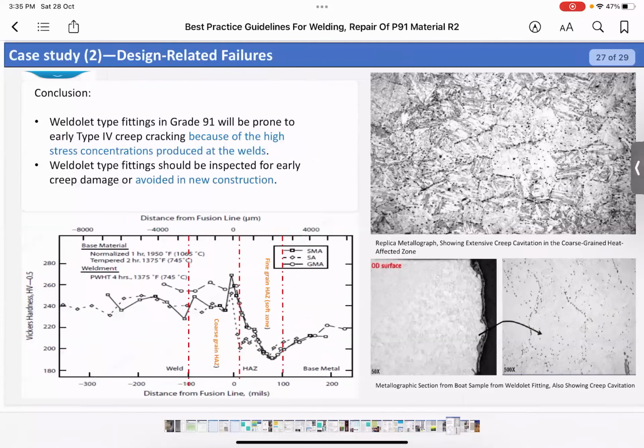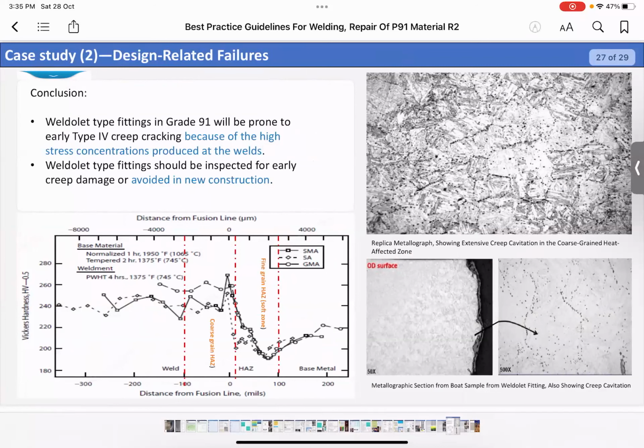As we see here, the creep voids in the microstructure, and the weldolet was concluded to be prone to early type 4 cracking because of the high stress concentration produced in the weld, and weldolets should be avoided in new construction. Forged T should be used.